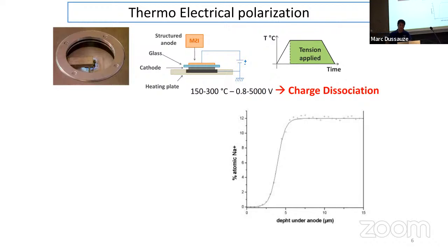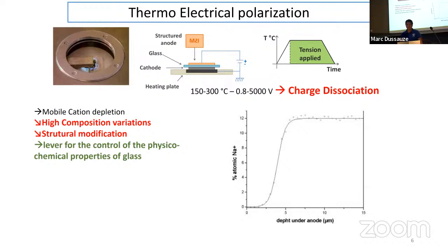And one good example of this charge dissociation is the typical depletion layer in mobile cations that we observe at the anode surface. So you can see here at 0, I hope you can see my mouse, this is the anode surface. Then you go inside the glass. This glass at the beginning had 12 atomic percent of sodium, and during the process, you have removed all the sodium in these small layers.